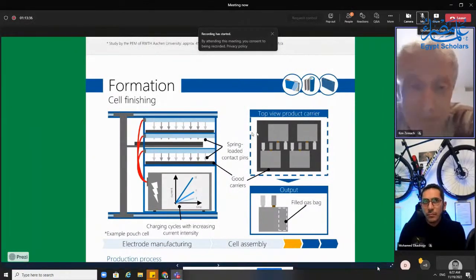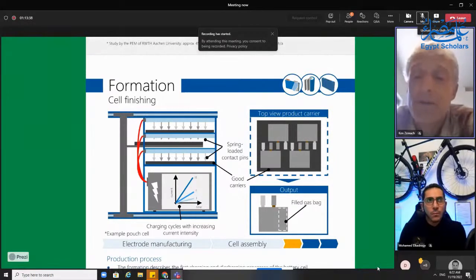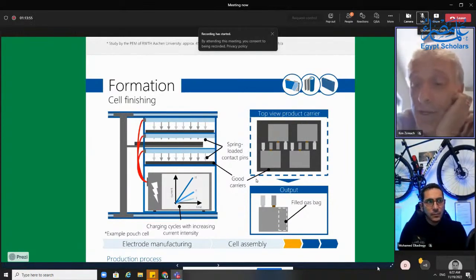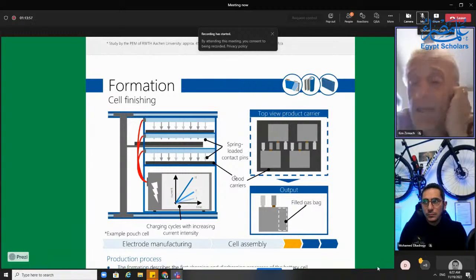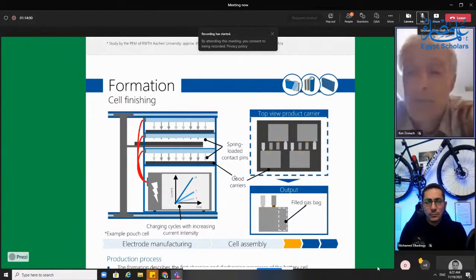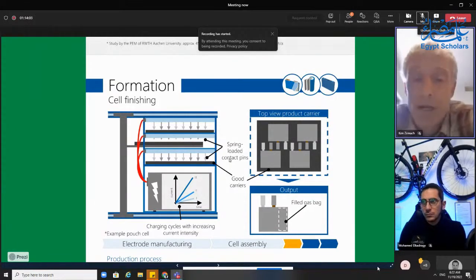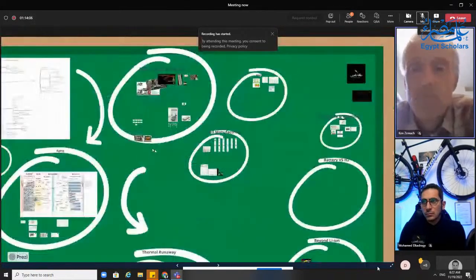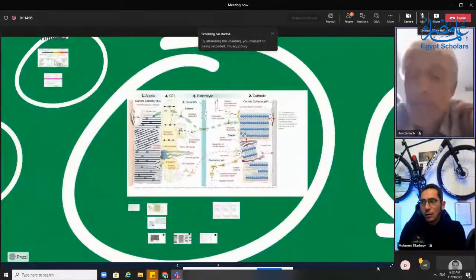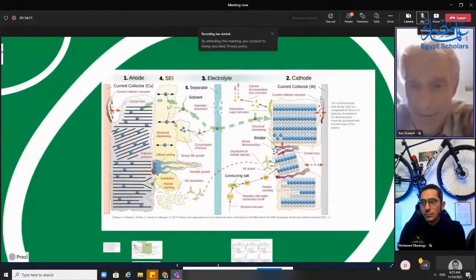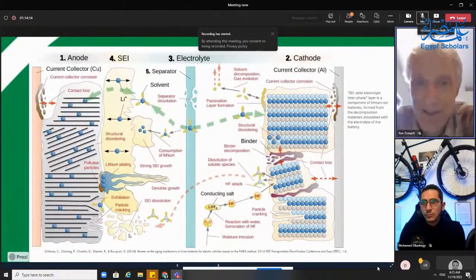What happens in that, your electrolyte does some electrochemical degradation on the anode. It creates what we call an SEI layer, a solid electrolyte interphase. Some people call it solid electrolyte interface. I think phase is the correct term, but people use them interchangeably. There's no standard. This SEI layer happens. You can't stop it, but it also turns out to be a protective mechanism. But when an SEI is formed, you also get gas given off. It creates gas.